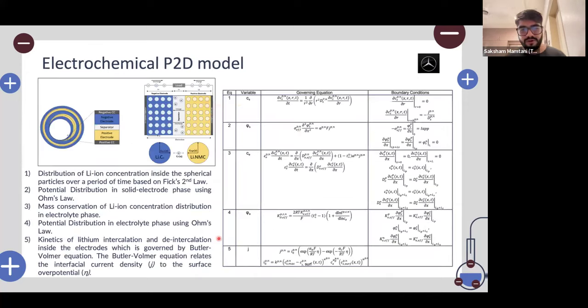Moving on to the final slide, I would like to talk a little bit more on the P2D model and how it is developed. So there are technically five equations which govern the working of this model. Those are two equations for Fick's law, the potential distribution in the solid electrode phase as well as the electrolyte phase, and the final equation for the kinetics of the lithium intercalation and deintercalation that takes place inside the electrode, which is described by the Butler-Volmer equation. So the whole model is based on these five equations, but it requires probably around 20 to 25 parameters to develop this model initially.